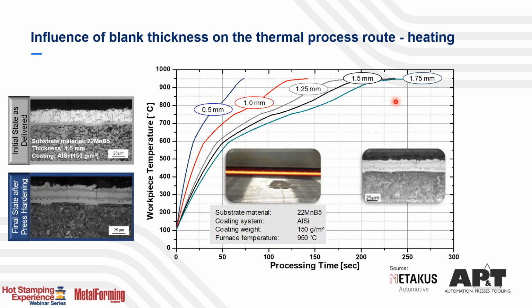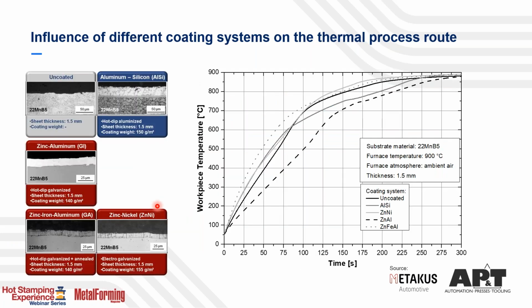Also good to see if your thermal measuring equipment, thermocouple, is working, because you see those little humps here. The first hump is when the aluminum silicon coating is melting at roughly 600 degrees. It's a change in surface. It's also a parameter that has an influence on the heating curve. And then we have the Curie temperature here at roughly 730 degrees. The next peak or change in the slope in the heating curve.